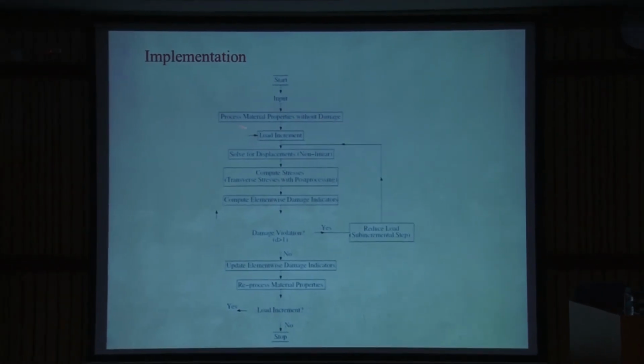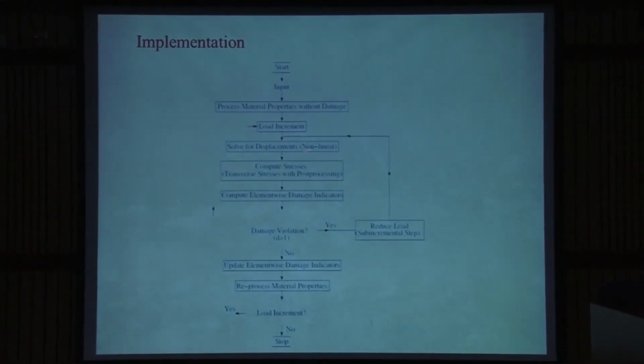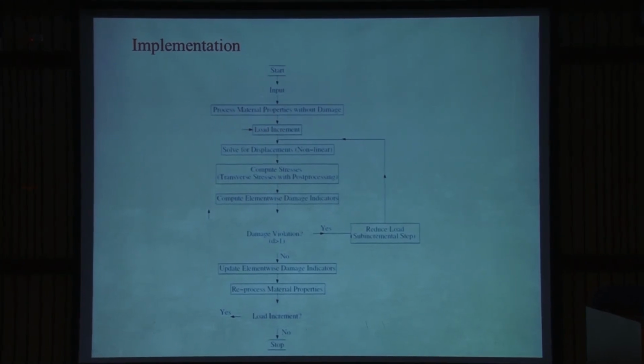With this, we will now see how it has been implemented. You have the input data on all these things. Process the material properties without damage, then go for the load increment. Then you first solve for displacement, which is non-linear because of the damage. Then you compute the stresses. Once you compute the stresses, from these you go back and find the strain energy of the damaged ply or interface, and then you find the damage indicator.